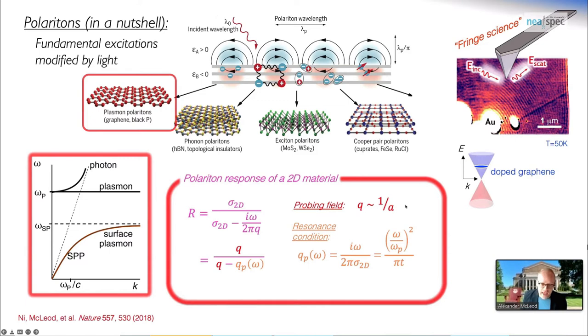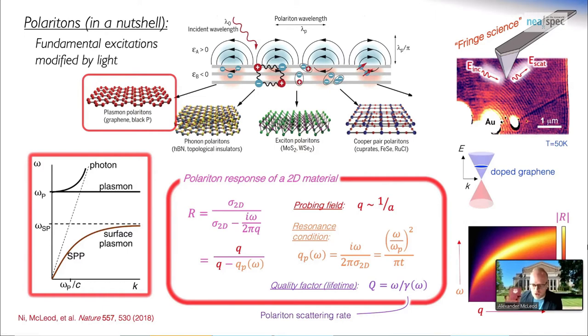Here we can typically, with near field, probe with very high momenta fields of order one over the tip radius, which I'm going to write A here, capable of exciting these polaritons. Most importantly, the resonance condition we can well describe by a plasmon momentum, which can be parametrized in terms of the two-dimensional conductivity. This formalism works perfectly well for quasi-two-dimensional metals, for which we have some finite thickness and a plasma frequency. In this case, we can devise a plasmon momentum which we might expect to excite a polariton resonance in quasi-two-dimensional metals as well.